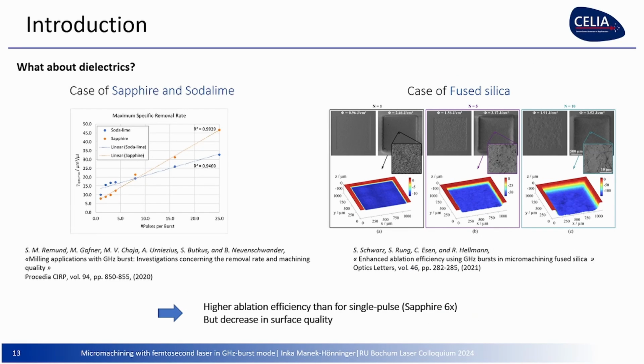Later on, some people were working on dielectrics, also cavity milling and ablation experiments. For example, the group of Beat Neuenschwander observed in sapphire an enhancement of 6 times higher ablation rate in the burst mode. However, that was to the detriment of the surface quality. This was confirmed by another group in these nice Optics Letters. You see, the ablation rate increases, but there was a detriment to the quality.